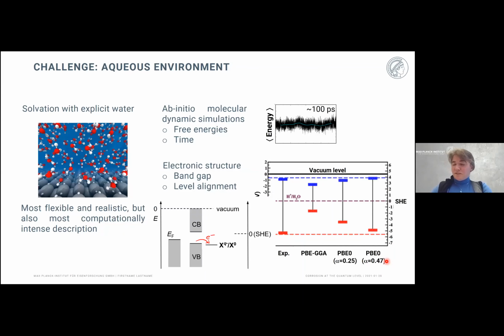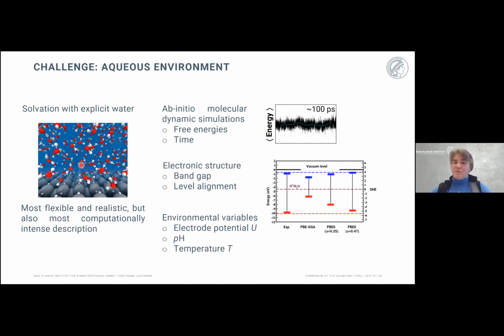So what are the consequences? Of course, we always need to be very critical of our simulations, but let's imagine in the context of corrosion or any kind of process what may happen. If we have here a metal, we have here a semiconductor, and we have here some redox level for a reaction. Now, if the valence band maximum is above this reaction level, then we may have an electron transfer, and this reaction may actually occur. But if we have this situation, then an electron exchange may not occur, and this reaction may not happen. So depending on how well we describe our electronic structure, we may find some effect or not. And therefore, we need to be really careful of what we are doing.